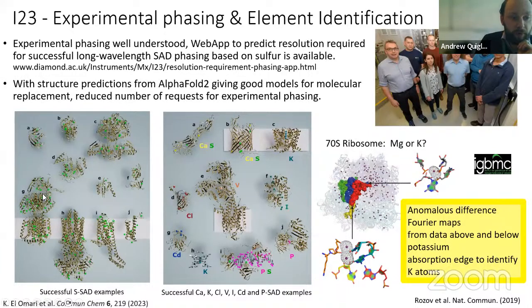So obviously initially we're doing a lot of experimental phasing. That's now mainly shifted. There's some cases where we need to do experimental phasing, but with AlphaFold it's less needed. But what we can do is tell you what elements you have within your crystals. So we could look at potassium, calcium, sulfur, vanadium, chlorine, cadmium, and so forth. One set of users had a project where they wanted to know whether it was magnesium or potassium that was bound within the ribosome, and we were able to show with the potassium absorption edge that this was actually potassium.